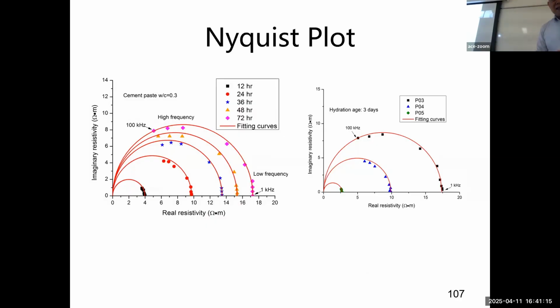And my fifth student used this technique to measure the Nyquist plot for this cement-based material. A very good thing is that all the plots go to zero, because there's no contact, so there is no capacitance effect from the electrodes, so it can go to zero.